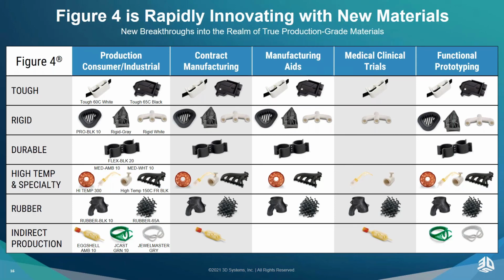One of the things about this particular material, this is a durable material. It's got a tensile modulus down around 800 to 1,000 megapascals, flexural modulus in that range. And then your notch impact is up about 91 joules per meter. So you've got a really tough, durable material because it's got that give to it because of the low tensile modulus, but it's got that really high elongation and it's got a really tough impact resistance with that 91 joule